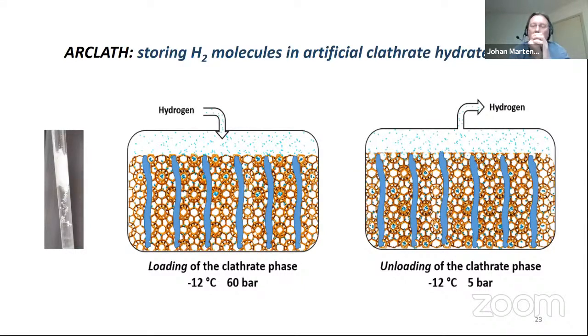The best known clathrate hydrates are the methane ice. You can also store CO2 in that kind of structures. Hydrogen is a difficult one. If in the bulk you would like to store hydrogen in a clathrate, you would need 2000 bar or very low temperature, so it would be very impractical. We discovered a way to do this, and it's using these blue features in a tank. With these blue features, you can make hydrogen clathrates at very attractive temperatures and pressures like -12 degrees and 60 bar.